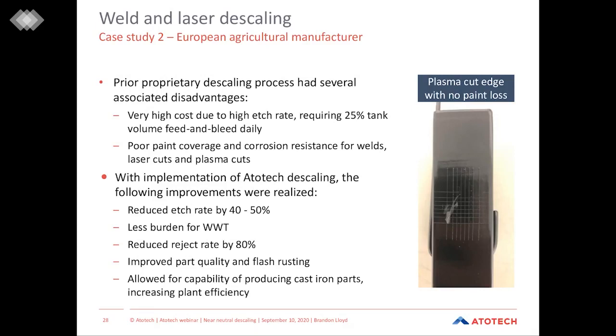With implementation of Atotech descaling with Uniprep AC, the following improvements were realized. They were able to reduce the etch rate by about 40 to 50%. There was less burden on wastewater treatment. It reduced their reject rate by about 80%. It improved their part quality and flash rusting. And it allowed for the capability of producing cast iron parts, which they were previously not able to do. And it helped improve their overall plant efficiency.